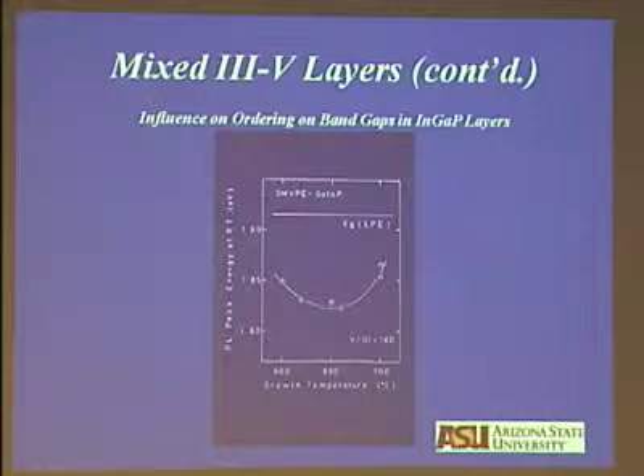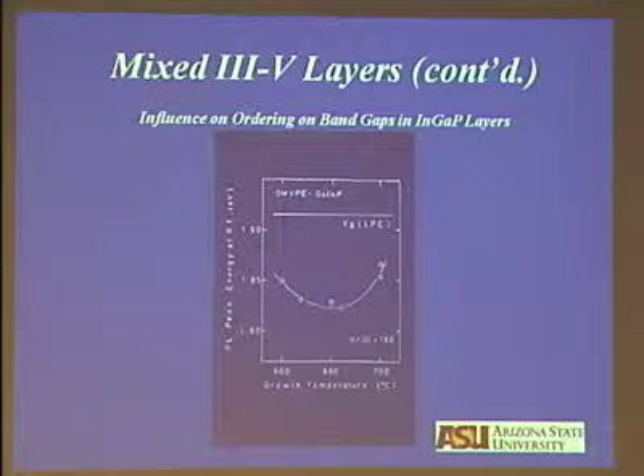All right. So ordering occurs on the 111 planes, and it is stress-induced ordering because of the surface reconstruction. And the size difference is needed to selectively put atoms in certain sites. Our conjecture is that phase separation occurs first, and then there is a movement of atoms over very short distances to produce the ordered structure. We never get an order parameter of 1. The best we could do was 0.5, because the time is too short to convert the phase-separated structure into the ordered structure. And that's what we observed.